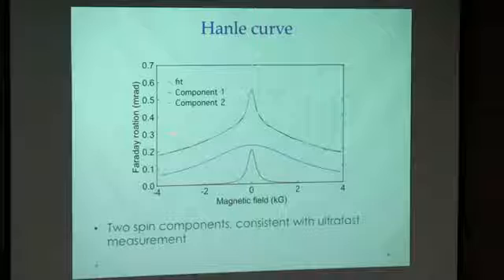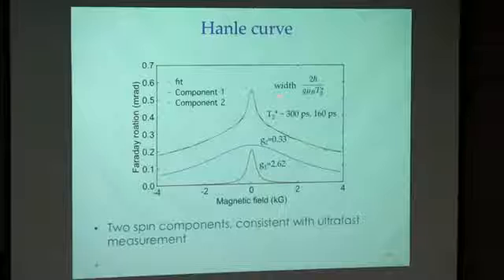And that's typically a Hanle effect curve that we measured. So this effect, where the spin cancels out in a steady state measurement, is called the Hanle effect. And this curve can be decomposed very well into two Lorentzian peaks. And from that we can, again, find out the lifetime.